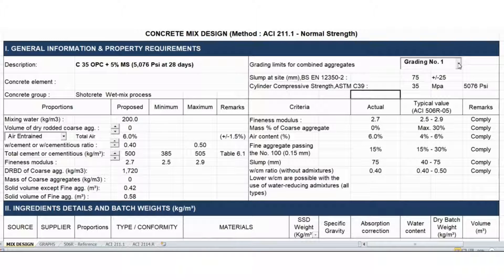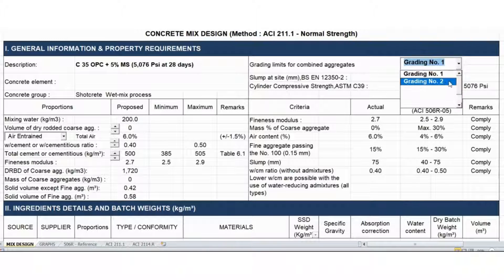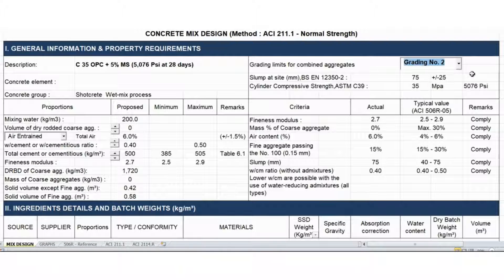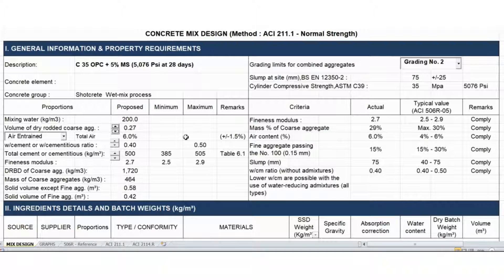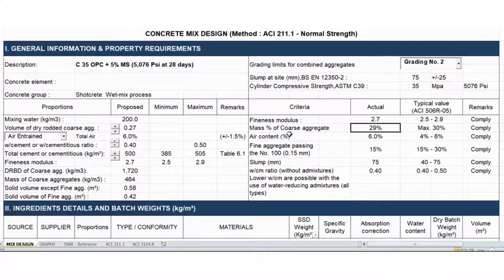We can also try grading number two with coarse aggregate. This time I have to increase the volume of coarse aggregate — let's say 0.27 — to give us 29% mass percentage of coarse aggregate.